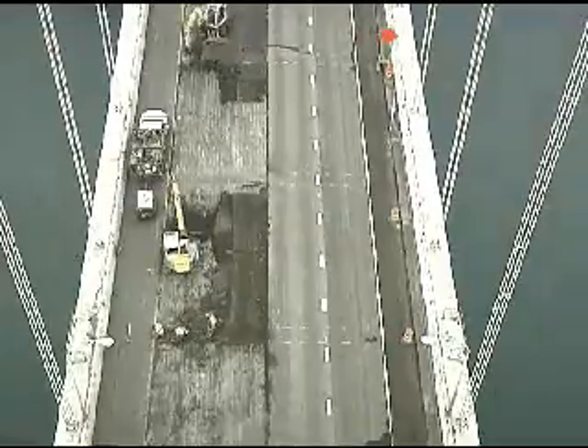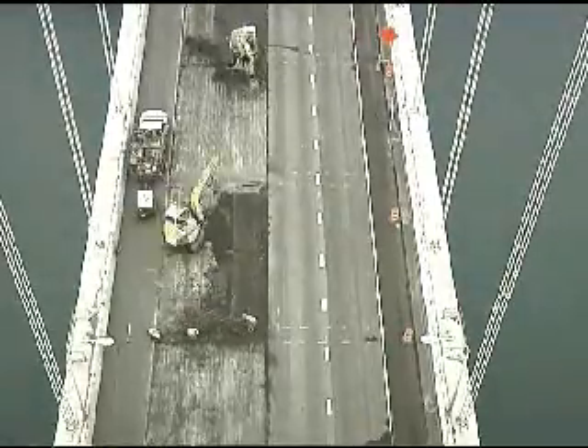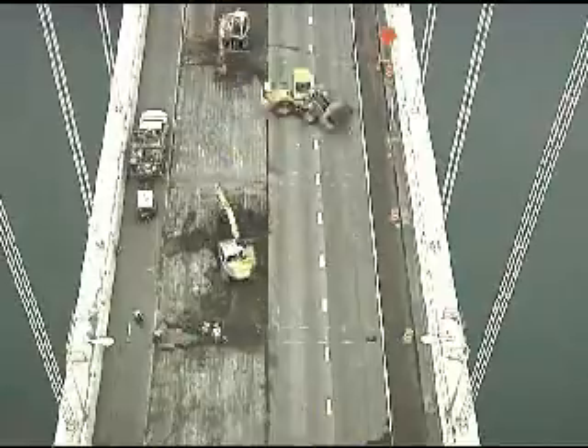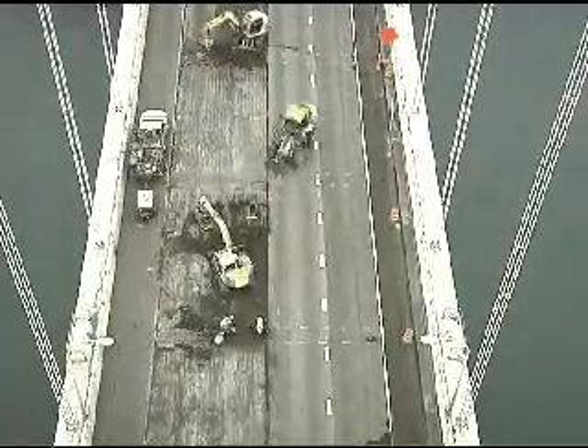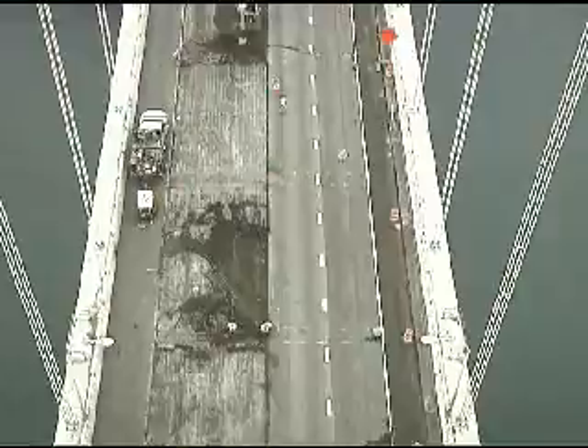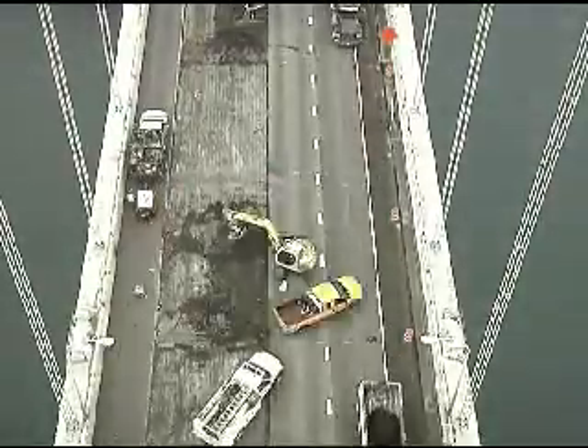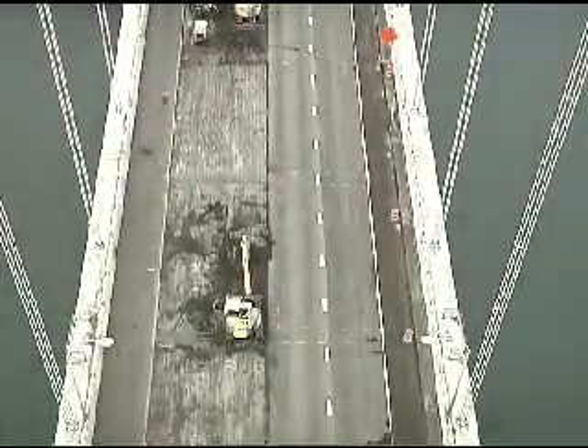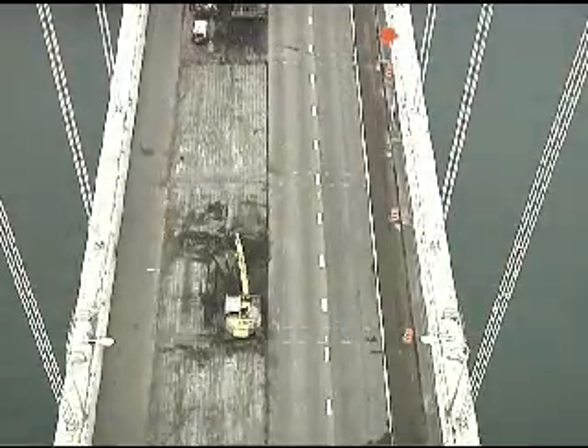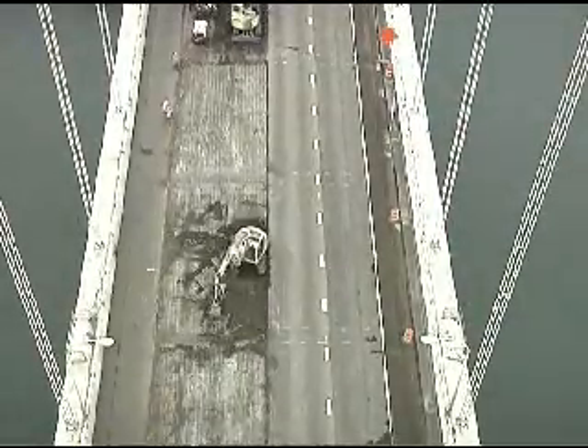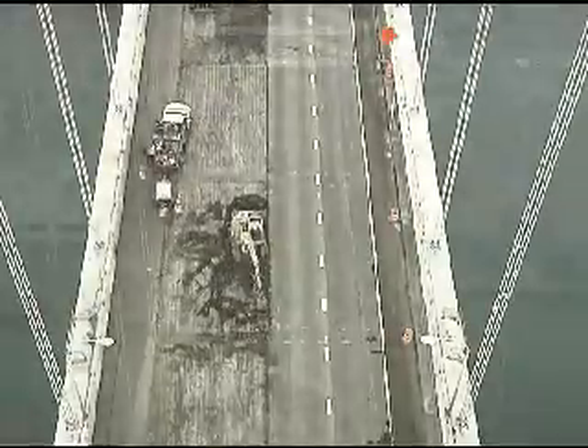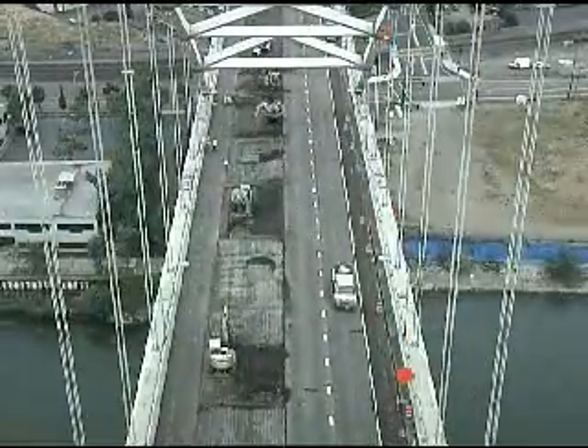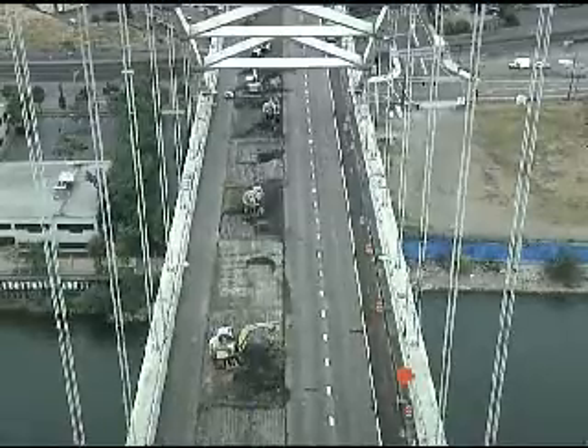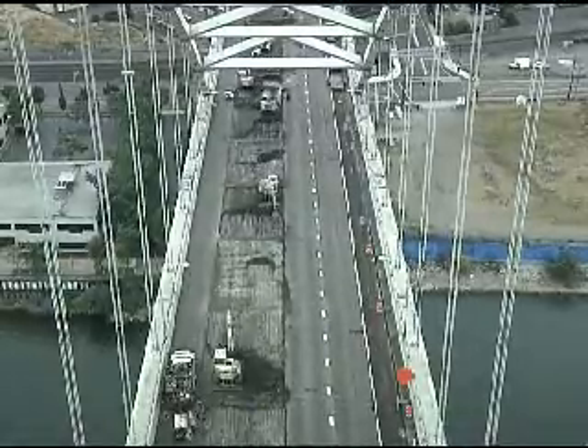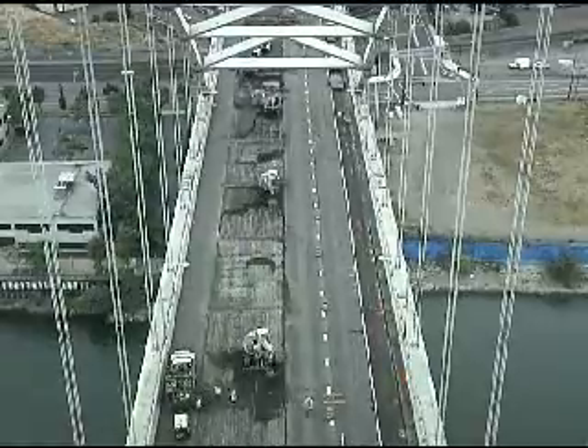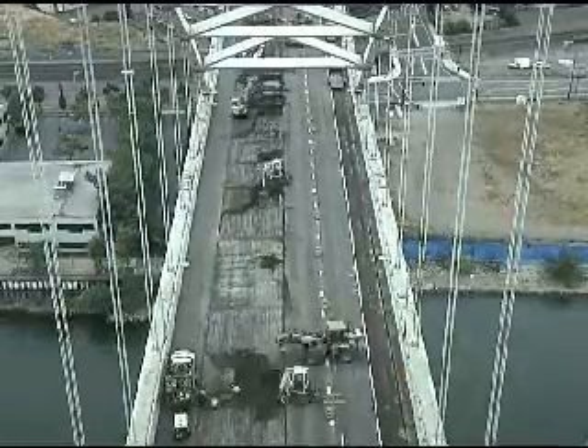In addition to the epoxy asphalt, there are layers of what we call epoxy bond coat. That's a spray-on product that acts as the glue that holds the epoxy asphalt to the steel deck, as well as we put it between layers of the epoxy asphalt. Our project calls for placing two layers of epoxy asphalt, a base lift and a top lift. And the epoxy bond coat goes between those two lifts as well as on the steel deck. The epoxy bond coat is a very strong, very durable product intended to reach strengths of around 300 psi pull-off strengths. It will really help this epoxy asphalt adhere to the steel deck.